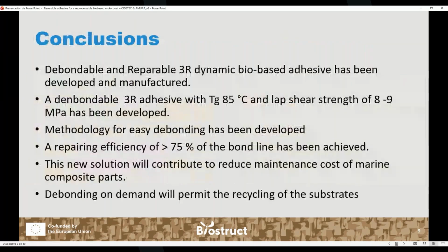And to conclude, as a summary of the properties obtained in this BioStruct project, we have obtained a debondable and reparable dynamic bio-based adhesive. This debondable adhesive has a TG of around 85 degrees and a shear strength of around 8 to 9 megapascals. Now we are working on the methodology for easy debonding, and we obtain a repairing efficiency higher than 75%. And this new solution will contribute to reducing maintenance cost of marine composite parts.